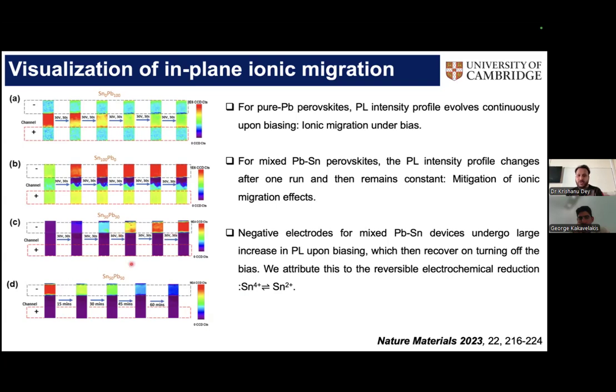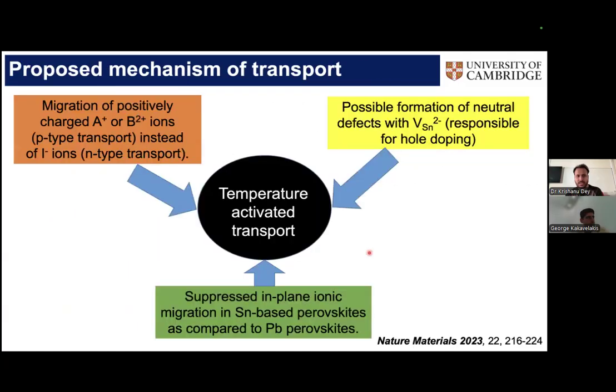But when you don't have that voltage, the tin doesn't want to be in that state, so it goes back to tin 4+, and therefore the PL decreases. So that's where we come and propose the hypothesis. But long and short of the story is that what we find generally in these tin-based perovskites, the lateral ion migration is significantly suppressed as compared to the pure lead-based perovskites. And then we propose some mechanism why this could be happening.